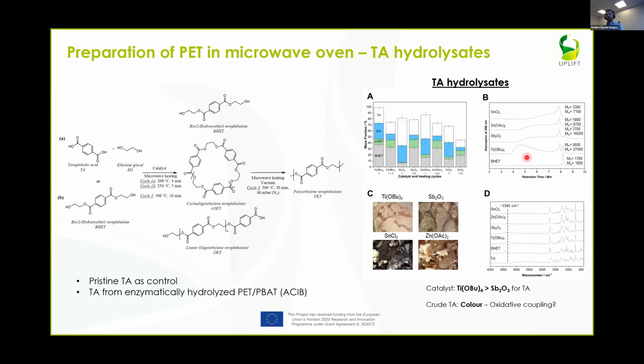The color of these polymers is not always perfect in terms of new polymers. So you can see here in some cases we get a heavy discoloration from some of these, and we believe that this is related to oxidative coupling of some of these systems. But with the higher purity of the starting materials, we are able to convert these into polymers.